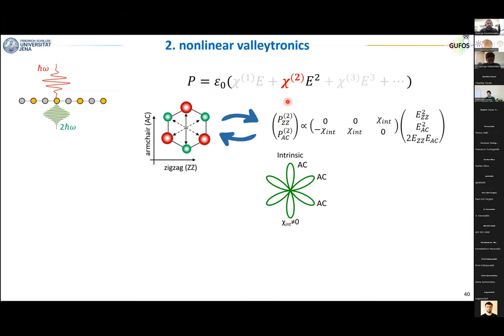Now, if I go a bit more into the details, sorry if there is a bit of algebra, but this expression here basically tells you that if we know that we have three armchair directions and we know the polarization of the incoming electric field, so the incoming electric field can be either along zigzag or along armchair or along a superposition of the two, then the second harmonic will be emitted either along zigzag or along armchair. This graph here, the so-called six-fold pattern, is an experiment where you rotate the polarization of the excitation and simultaneously you rotate a polarizer in front of the detector.